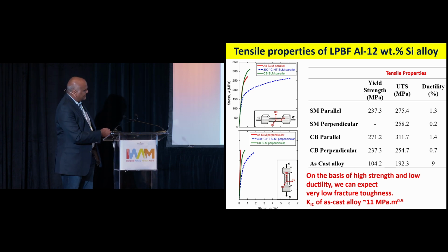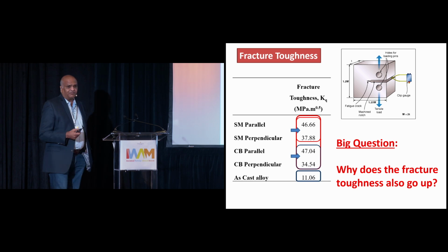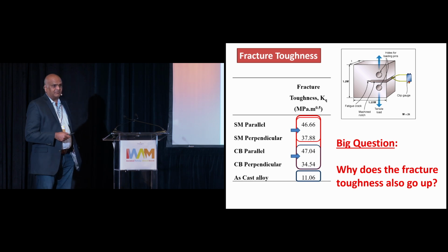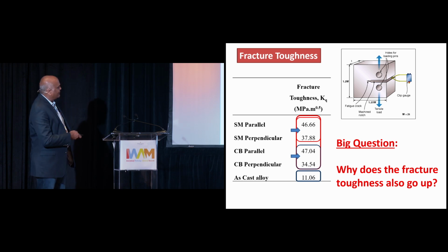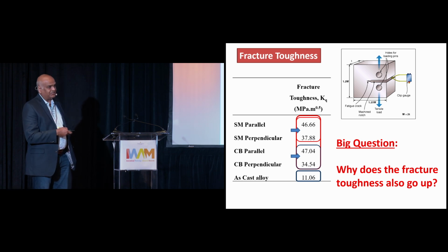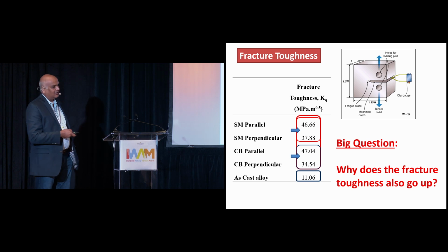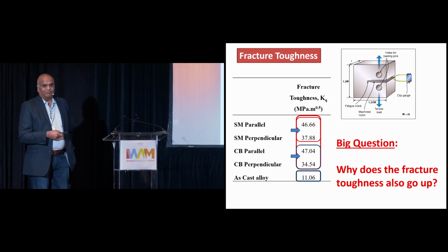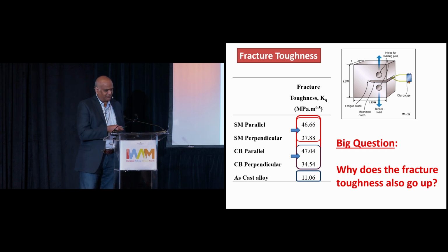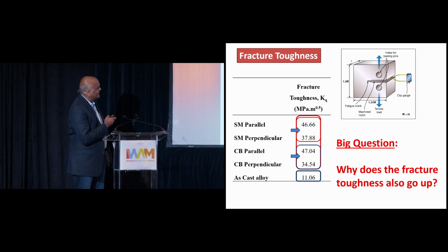So for reference, the as-cast alloy fracture toughness is about 11 MPa root meters. This is a unique thing. So when we did fracture toughness measurements, we were expecting it to be much lower than 10 MPa root meters. What we found is that the fracture toughness actually did not decrease, but actually went up. Strength has gone up by about 100%, but the fracture toughness has gone up by 300, 400%, okay? So these are what we call proper fracture toughness measurements, where we put a crack and measure these things.